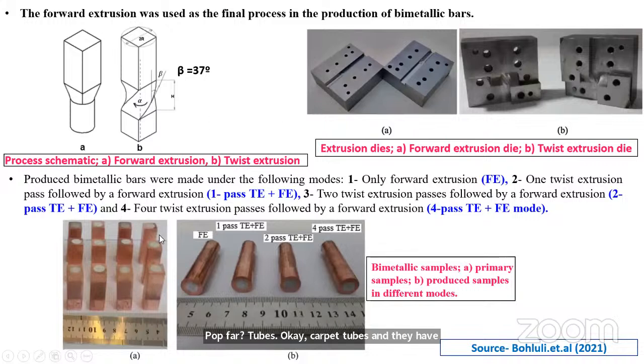Then they made the material pass through the twist extrusion process, where the material is twisted at a slope angle of 37 degrees and a twist angle of 90 degrees. They produced bimetallic bars under the following modes: only forward extrusion first, then one twist extrusion pass followed by forward extrusion, then 2 twist extrusion passes followed by forward extrusion, and 4 twist extrusion passes followed by forward extrusion. In addition to twist extrusion, they extruded once again with forward extrusion in order to regain the homogeneous condition of the material.